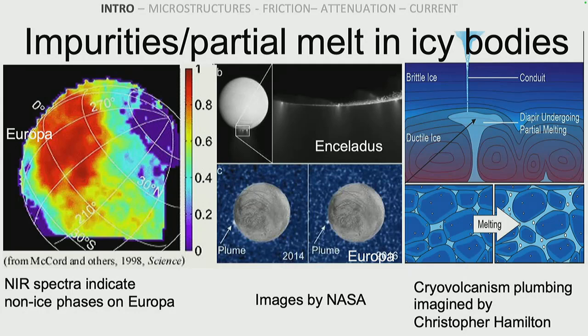And since others are working on high pressure systems, our niche in the world, where we're trying to be at the forefront, is thinking about impurities. The various missions that have gone out have identified with infrared spectroscopy that there's more than just pure ice on these moons. There's various kinds of hydrated salts. No one salt is a perfect match to the spectra, so there's a laundry list of possible ones. And our lab has been spending time thinking about some of these different systems and how having that second phase could reduce melting temperatures and create partial melt. And we see things that look like volcanism and impurities on the surface. So that motivates why we're looking at this.